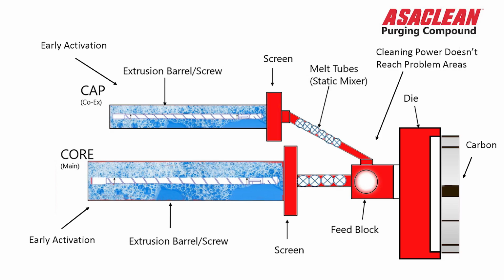Chemical purge compounds are heat activated. They typically begin the chemical activity around 360 to 380 degrees. But for every 30 degrees you add, the chemical activity almost doubles. At 550 degrees, you are getting the most chemical activity out of the product that it can generate. And it's also time released.